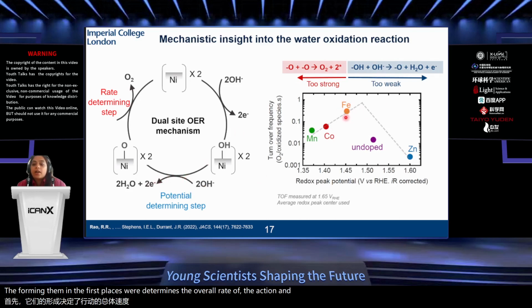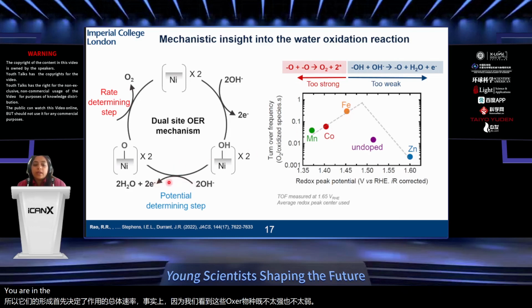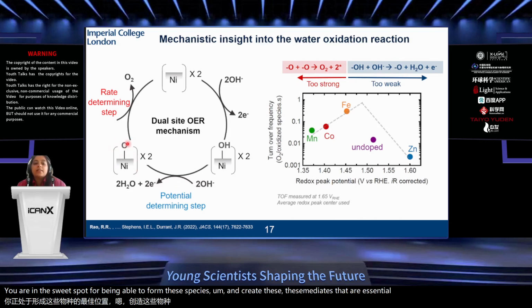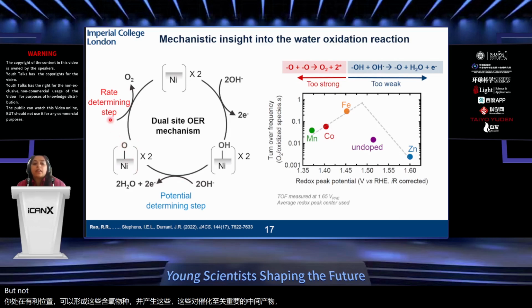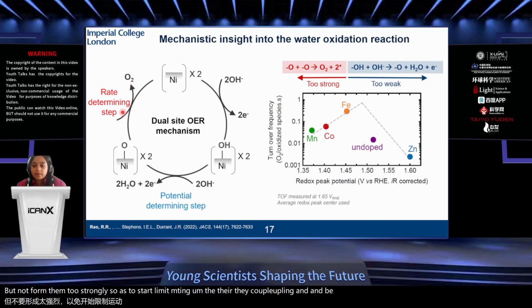And for iron, we see that these oxo species bind neither too strongly nor too weakly. So you're in the sweet spot for being able to form these oxo species and create these intermediates that are essential for the catalysis, but not form them too strongly so as to start limiting their coupling and desorption from the surface.